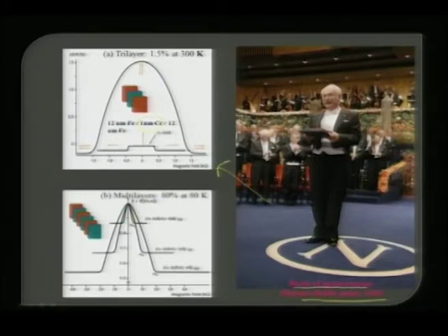In his report he said, if you take only iron of this dimension, say 250 nanometer, and measure the resistance as a function of magnetic field in both directions, you see a very small change in the resistance, which is called anisotropic magnetoresistance, of a very low order.